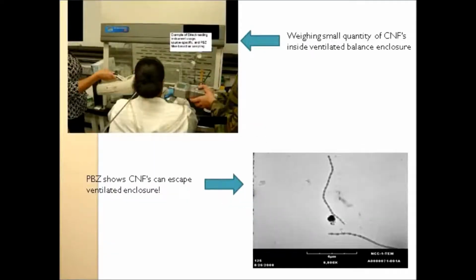Another example, this is a smaller scale research operation using a ventilated balance enclosure where she's weighing out carbon nanofibers, a little bit different. And here's some of the field personnel actually collecting particle number concentration measurements in her breathing zone, and that is also a probe. We're not probing her brain, but that's also another direct reading instrument, so we're kind of, unfortunately, swarming around these folks to get some readings while they're doing these tasks. And also, you can see the two tubes that run across her back. Those are the filter-based samples that are in her breathing zone.